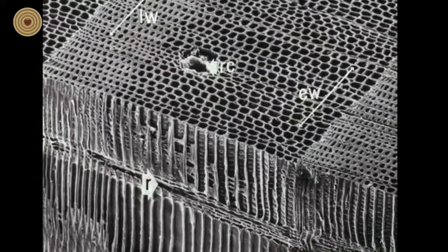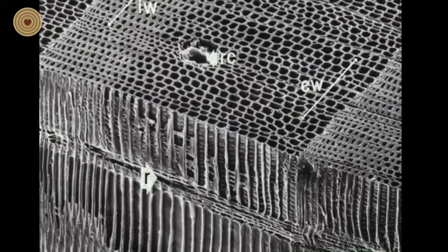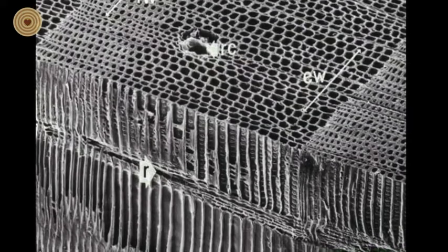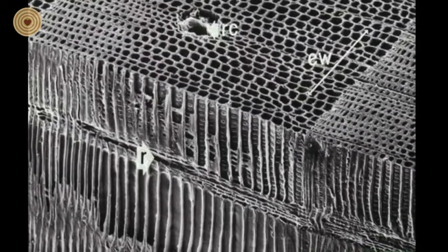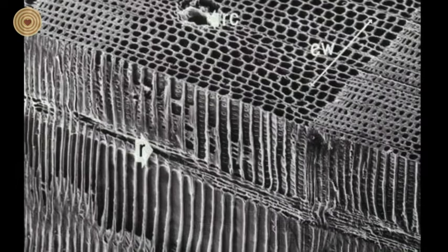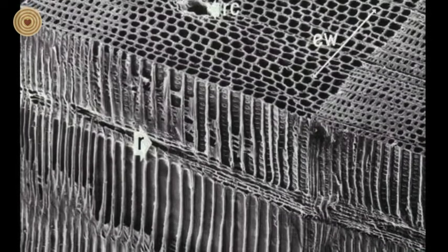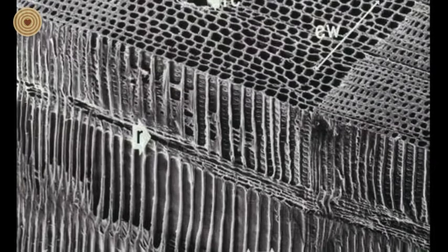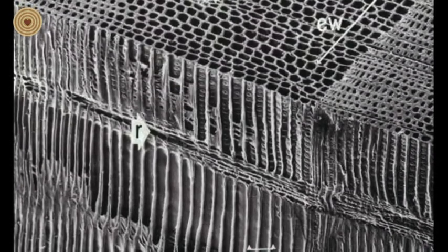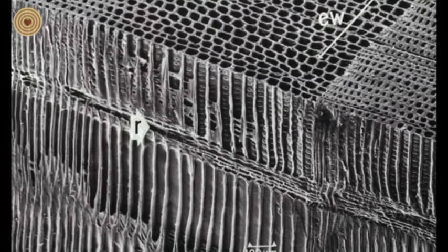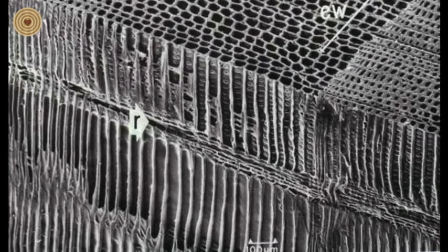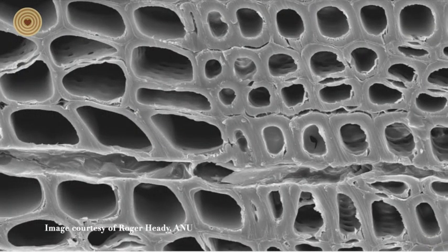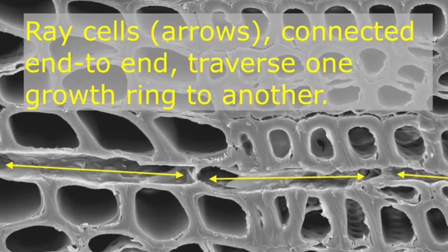The side of this block of wood shows the radial wood surface and on that radial surface you can see a ray or a series of ray cells that are labeled with the letter R. The rays are arrayed in the tree sort of like spokes in a bicycle wheel going out from the center and out toward the bark. The rays function to transport nutrients from the inner bark of the tree inward to the living cells that form what we know as the sapwood. Note that the rays extend completely across a growth ring and continue on into other growth rings.